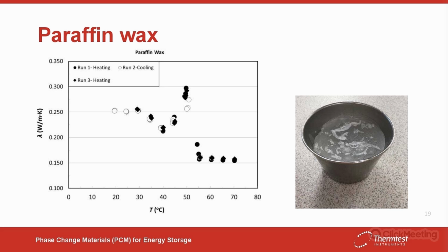You can see also that the results during the heating and cooling are very repeatable for both the liquid and solid phase, and this is because the solid phase is very homogeneous and there are no different surfaces that appear during the solidification of the paraffin wax.